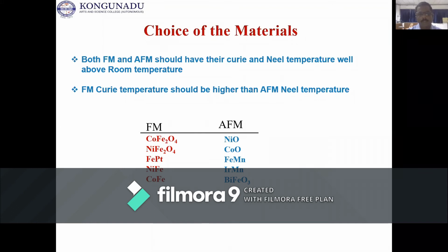In the literature, I can see room temperature ferromagnetism is achieved by using these materials, where iridium Mn and cobalt ferrite or cobalt FePt, Fe platinum structures have a good exchange bias coupling.